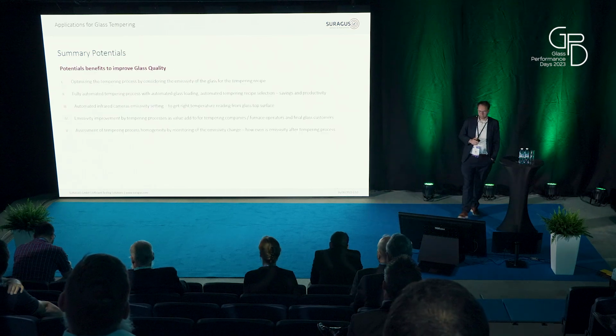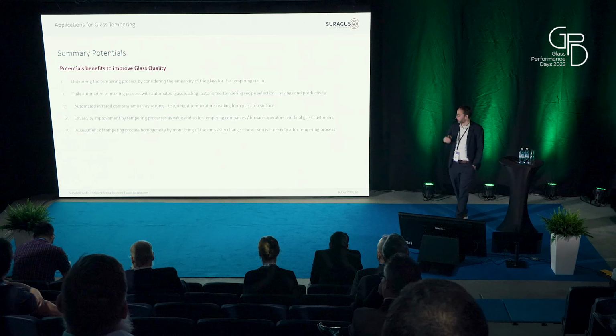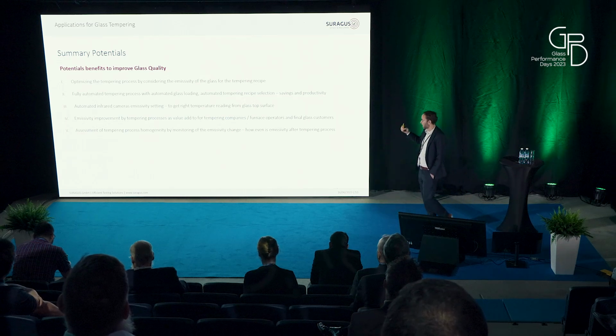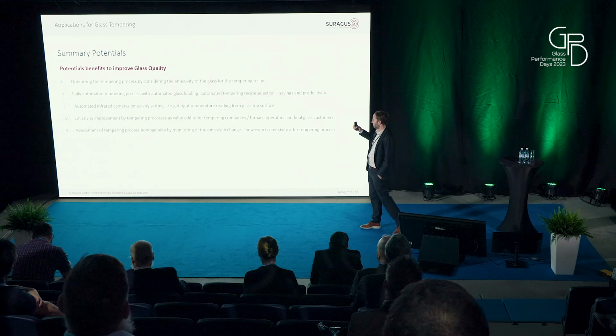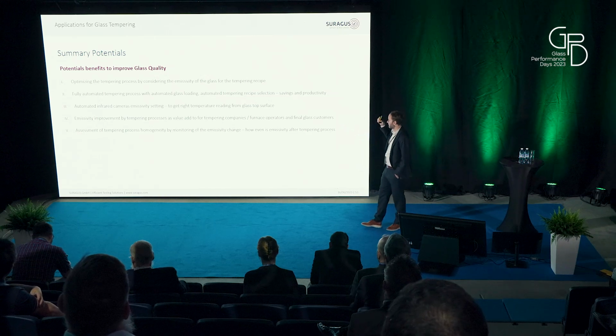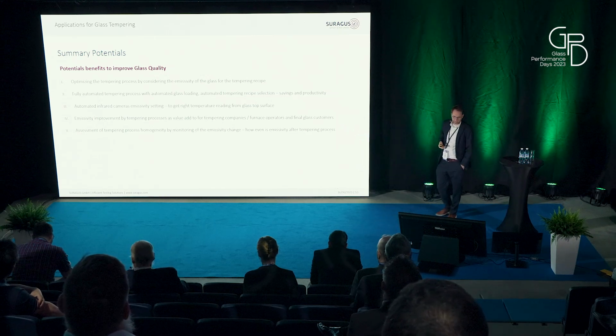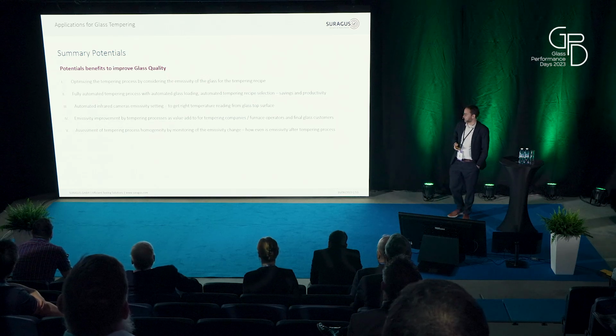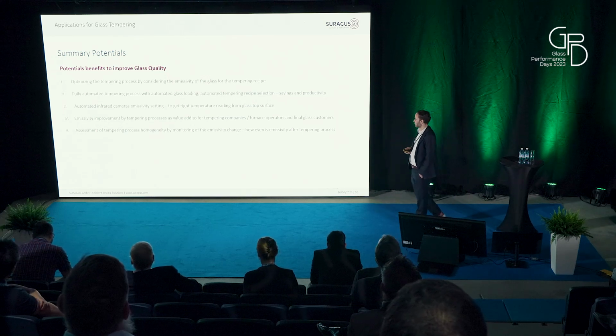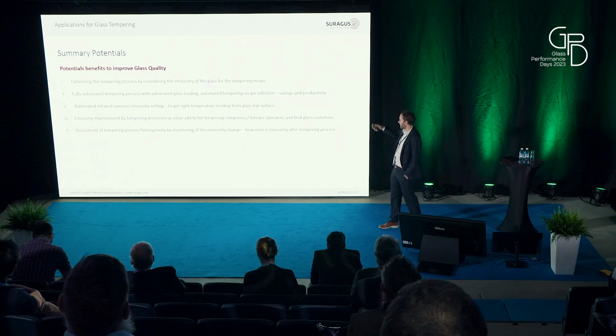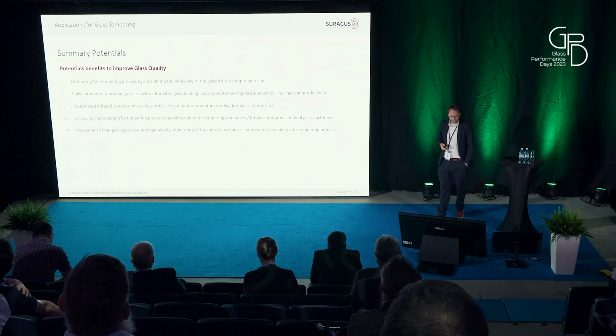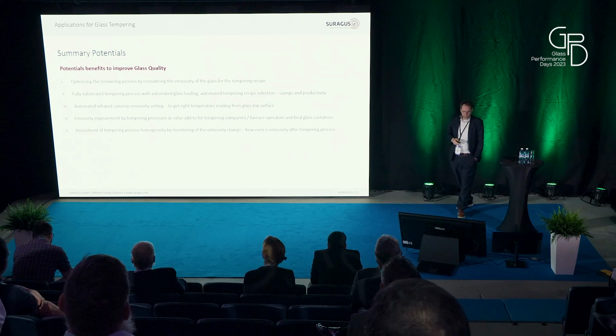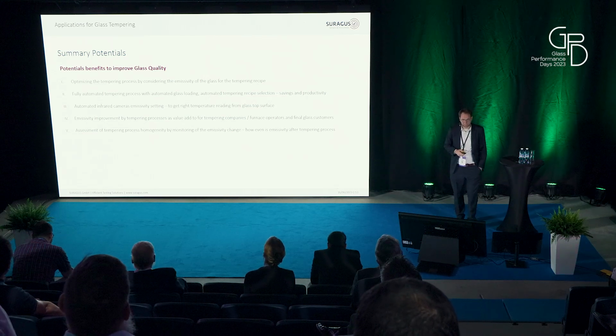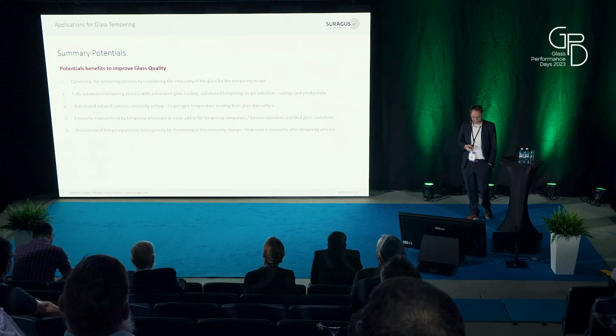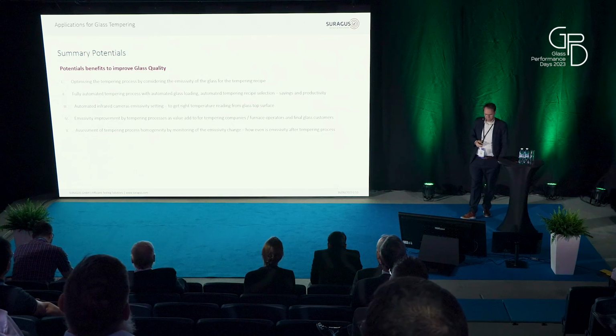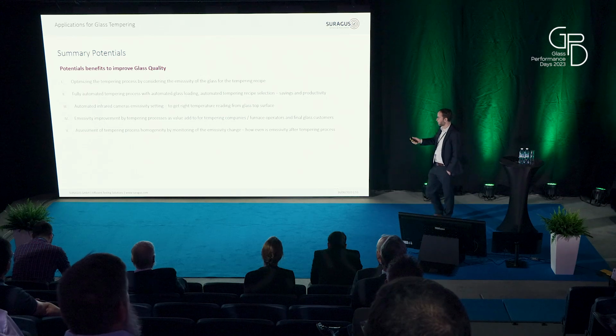The potential that we see is to optimize the analysis of the emissivity at the tempering entrance, and consider this very precisely for a very defined recipe selection and recipe optimization. Also to use this for fully automated process control and automated loading and unloading, so automated recipe selection and validation. Use this to improve the infrared readings of the temperature from the infrared camera. Use the emissivity improvement as value add. So there is a value add, often unknown.